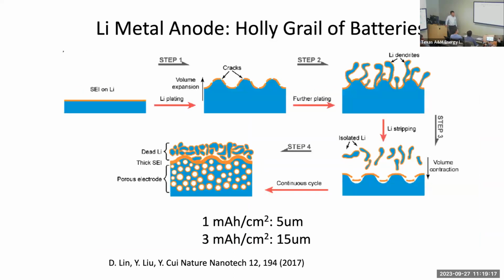So for the high energy density battery, what's next? We need to work on the metallic lithium anode. A metallic lithium anode has no host. It's based on metallic lithium foil plating and stripping, a very different mechanism from intercalation. If you take metallic lithium foil, it will form this SEI layer, solid electrolyte interphase, right, when put into organic electrolyte.